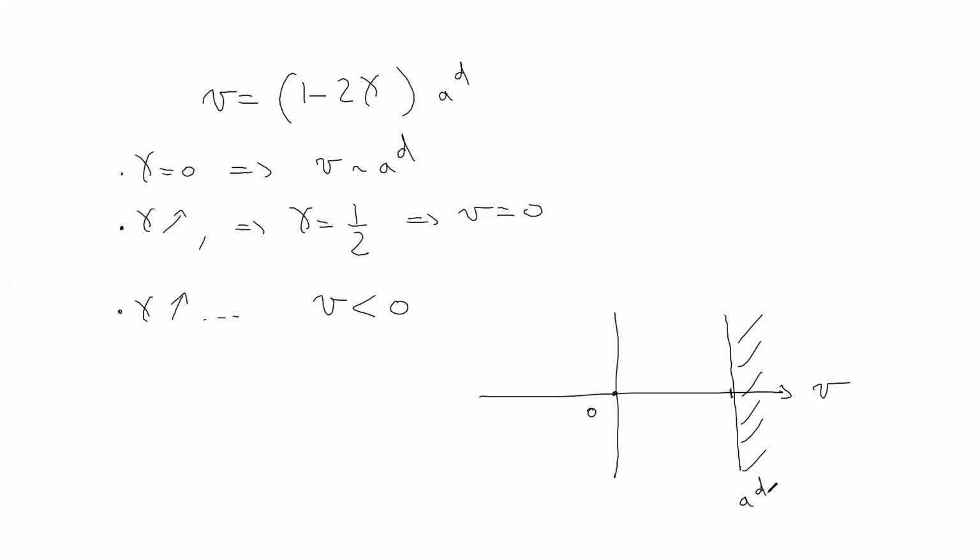Then by increasing gamma, you end up in a situation where you have a chain which is nicely swollen inside the solvent, to a situation where, if V is negative, it will collapse fully. You have a term of entropic elasticity that pulls you down, and you have an interaction that also pulls you down. So there is no balance anymore, everything collapses, and now you really have a stack assembly of molecules. Really everything is precipitating, if you wish. And the transition is for V equals 0 here.